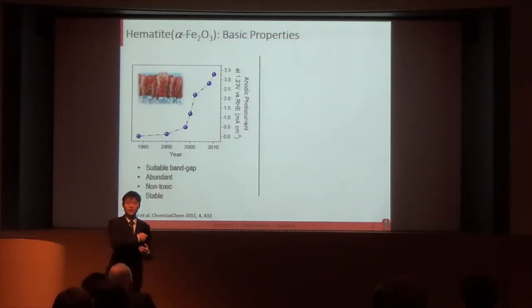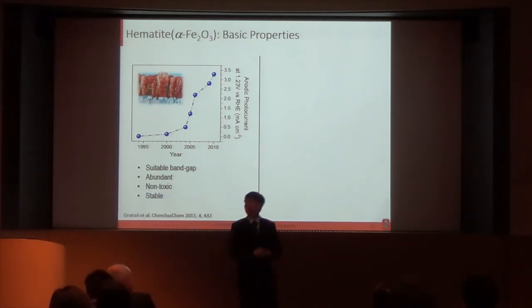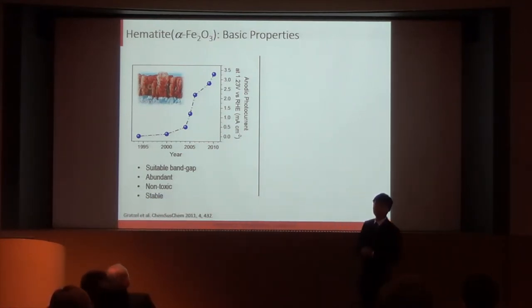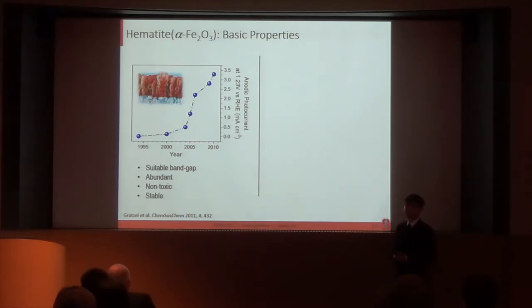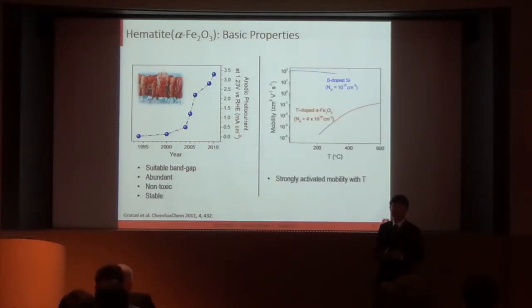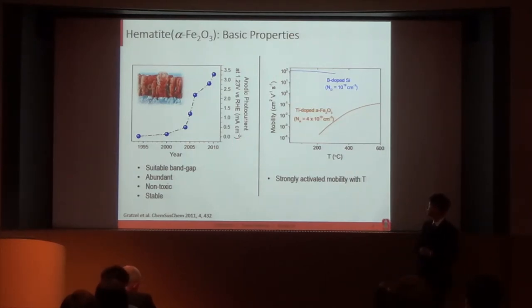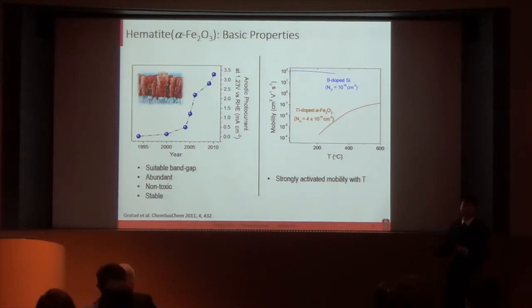The material that I chose in this study is hematite, or iron oxide. This material has been researched and improved as a photo anode for many years. It has suitable band gap for water splitting, it is abundant, it is non-toxic, and more importantly, it's thermally very stable. So that's why I chose this material initially for this study, because I don't need to worry about degradation at higher temperatures. A second reason, hematite is well known for its strongly activated mobility with temperature. So if you look at this plot, the mobility in hematite increases exponentially with temperature, as opposed to the slightly decreased mobility in silicon.